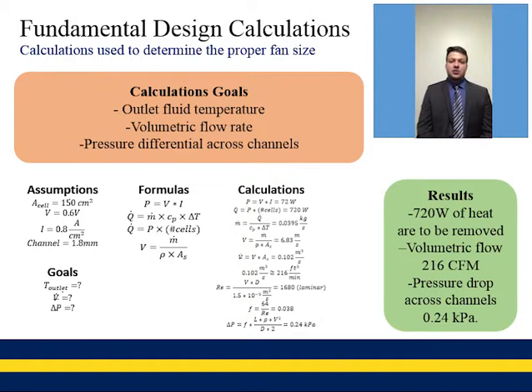The three results that we needed from these calculations were the outlet fluid temperature, the volumetric flow rate, and the pressure differential across the channels. Before we could run these calculations, we had to come up with a few assumptions. We assumed that the active area for each cell would be about 150 centimeters squared. The voltage from each cell would be about 0.6 volts, and the current from each cell would be about 0.8 amps per centimeter squared. Each channel in the cell would be about 1.8 millimeters in diameter.